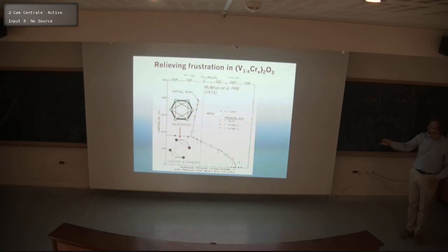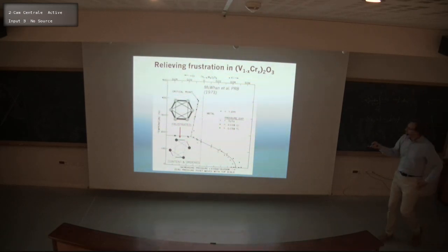This is a really high energy phenomenon, and the lattice is saying, let me just distort a little bit, and I'll be able to adjust all of the exchange interactions so that I can now satisfy the interactions. I get a long-range ordered magnet, coherent magnetic excitations, and so this is actually kind of a structural relaxation to relieve the frustration.